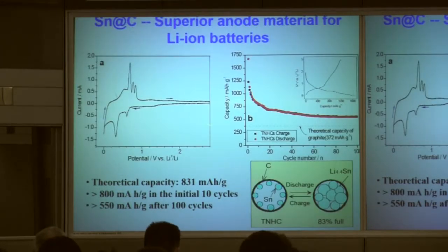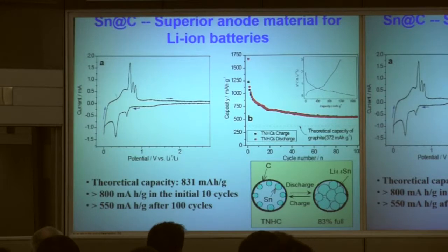We also measured the electrochemical property of this material. Here is the cyclic voltammogram. You can find the different peaks. That means different electrochemical processes happen at this potential and this potential. And also this peak is very sharp. That means the electrochemical process at this electrode potential is very fast.